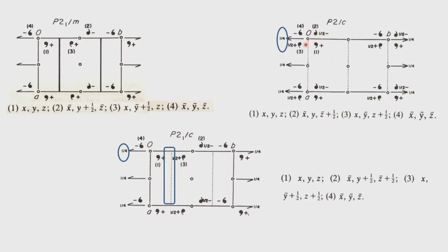So these two positions therefore have a half translation in a direction which is perpendicular to this plane of operation, and therefore it is not really perpendicular, it is along the C axis. So we have to remember that in a monoclinic system the third axis is not at 90 degrees, right. So this is now therefore going along the C axis, it is half translation along the C axis. Please remember the half translation along the C axis will not involve a 90 degree angle, which is very important in monoclinic systems. So it is moved by half the translation.